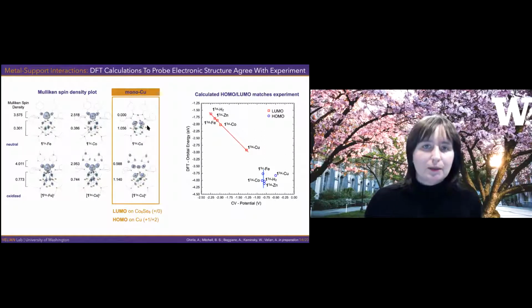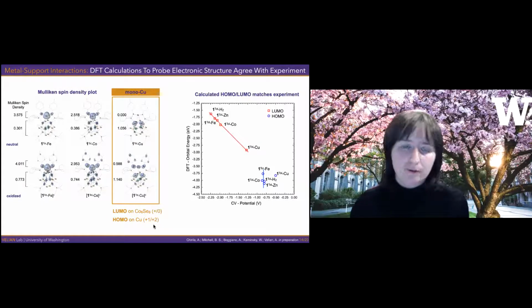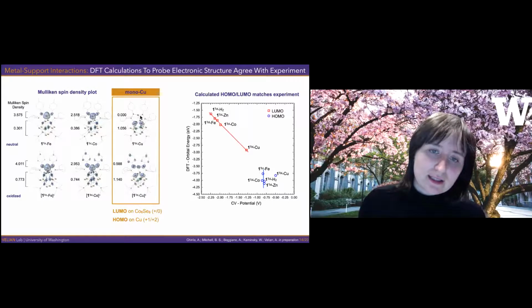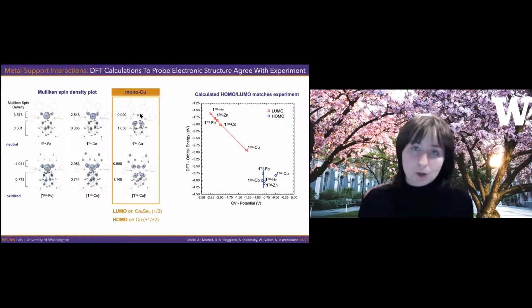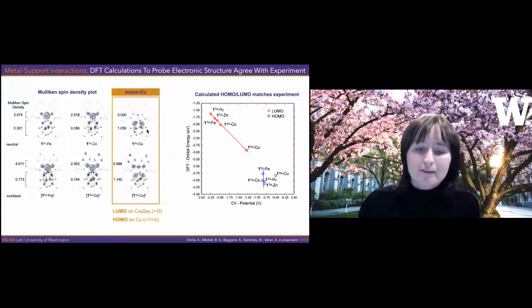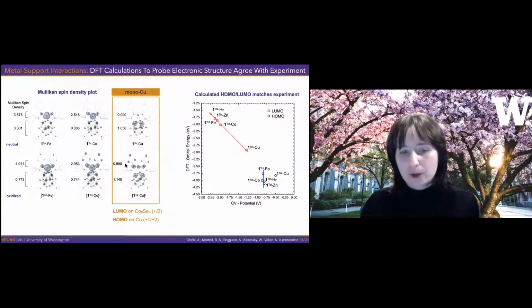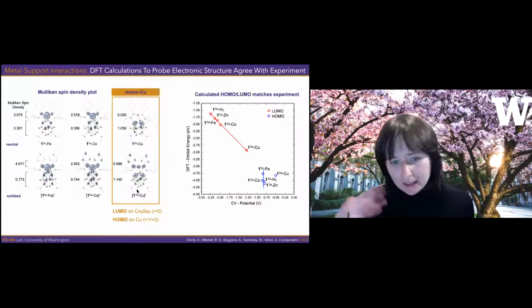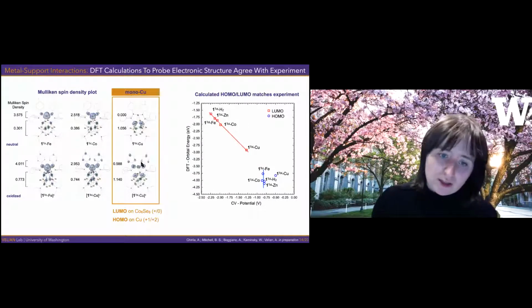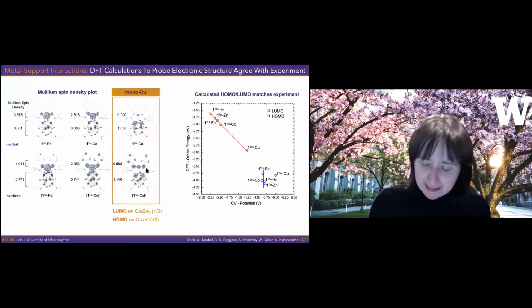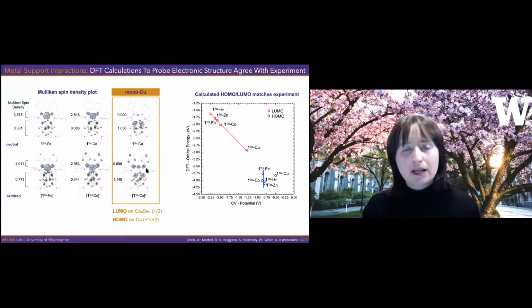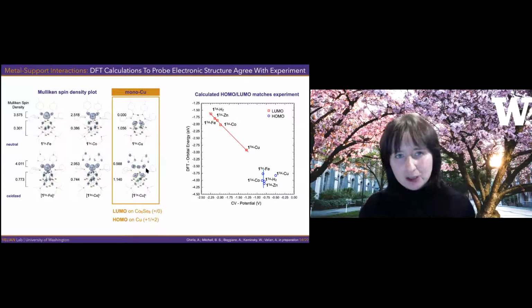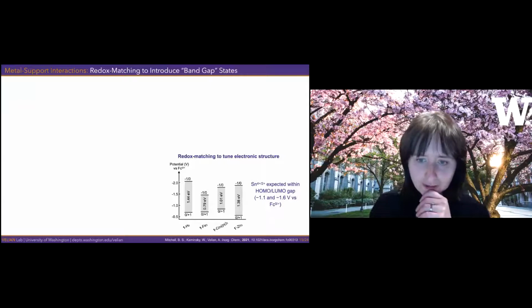And so what this tells us is that most likely what happened, the copper 2 has oxidized the cobalt core, and now my HOMO level and my LUMO level are different than for the other ones. Okay, so the HOMO level is this copper that is now copper 1. So if you oxidize it, you pull an electron from it, and then the LUMO level is now the oxidized cobalt core, not the neutral one. And this is also confirmed by what we see when we in silico oxidize the cluster. We see that in fact now we do observe spin density on the single copper. So that's just to give you an idea of how, by changing just the edge site, we can tune the electronic structure of our system.